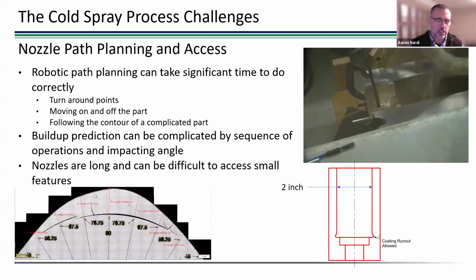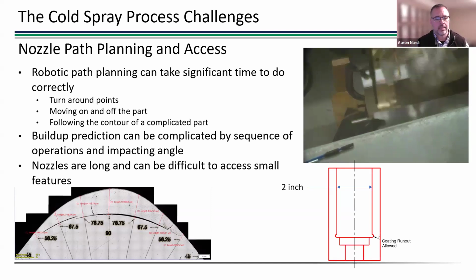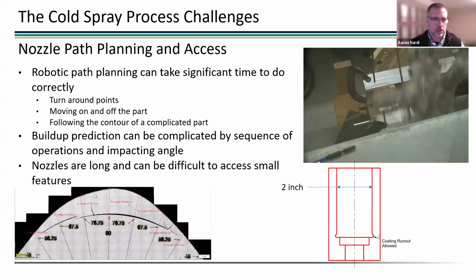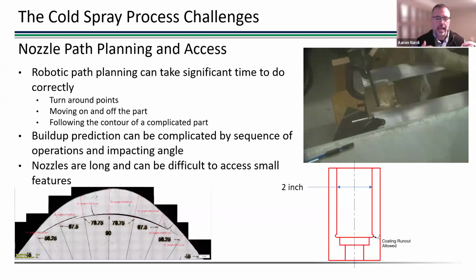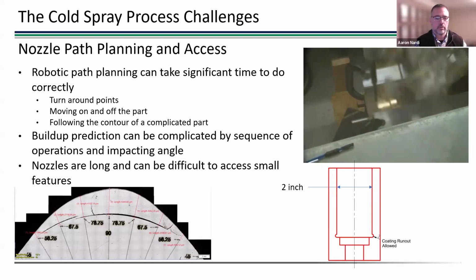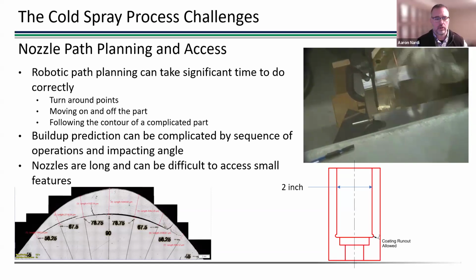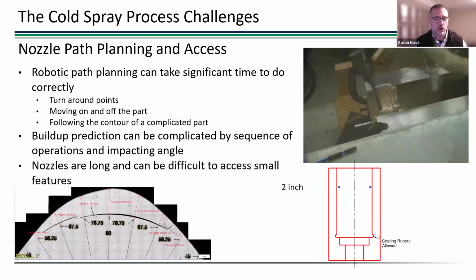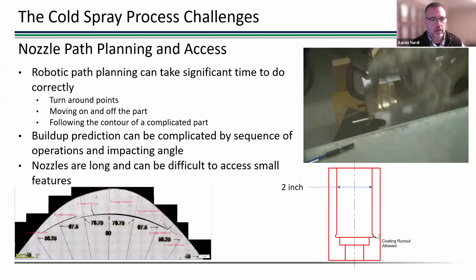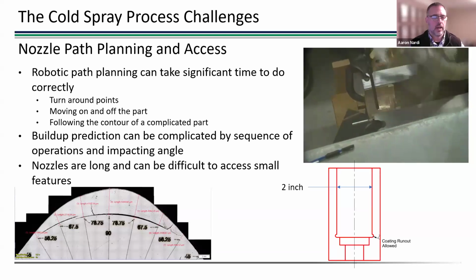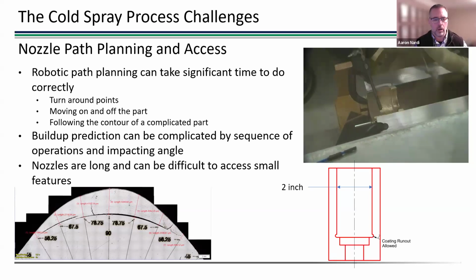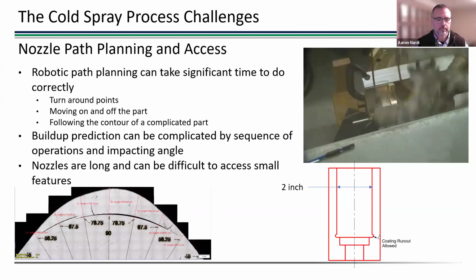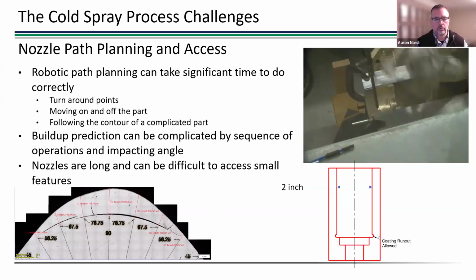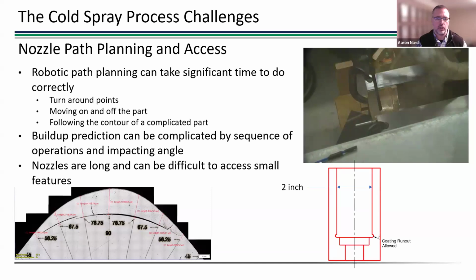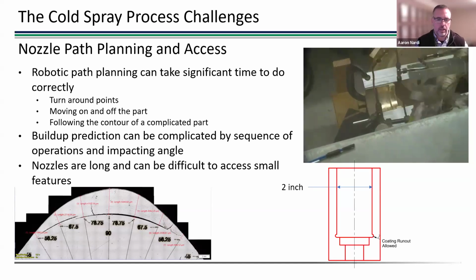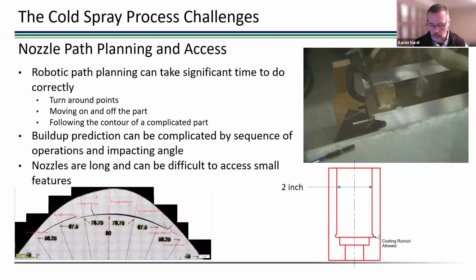So it may be tough to see, but the right-hand side of that deposit has a layered porosity structure where the left-hand side doesn't. And that's because of the sequencing of the raster pattern used on this part during the deposition. You also can clearly see the interface cracking, problems at the interface, again, because of how that material was laid down. And then the other thing I just threw on this slide is access. Like, how do you get your nozzle into a small area to try to access that small area?